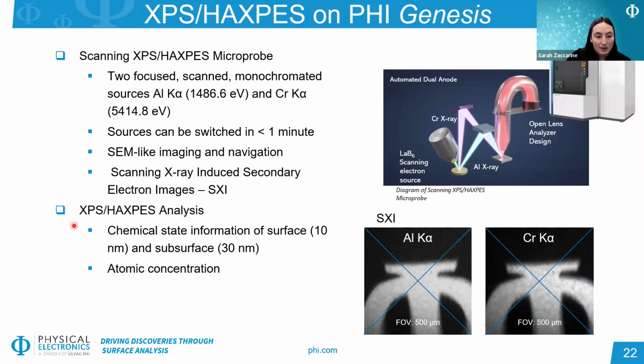Our XPS chemical sensitivity is more surface sensitive, up to 10 nanometers, and then the chromium source is probing about 3 times that, so about up to 30 nanometers. So this is the deepest analysis out of these surface analysis techniques that we've talked about. And these can also be used to look at atomic concentrations of both elements as well as chemical states.